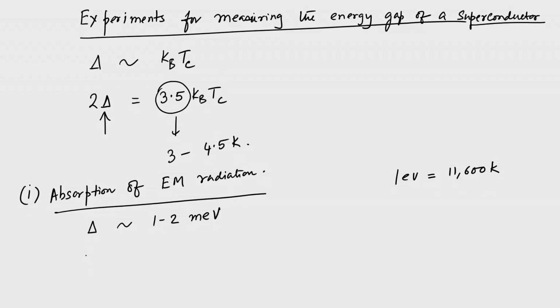So, if we want to use an electromagnetic radiation, the frequency should be, let us just write it, h nu has to match delta in order to break the Cooper pair. So, nu is delta over h, and this is equal to about, if you use 1 milli-electron volt, around 2.4 into 10 to the power 11 hertz. So, basically it is in this regime of 10 to the power 11 to 10 to the power 12 hertz.